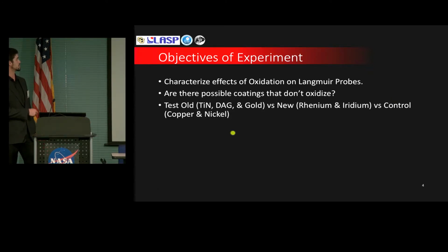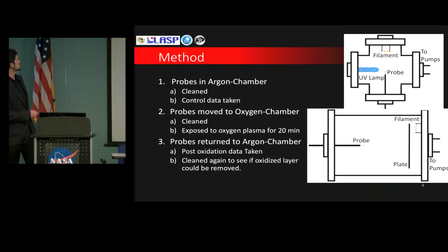And then we tested these against new coating materials, rhenium and iridium, in the hopes that those would not show any degradation. The reason we chose rhenium and iridium was that their oxidized layers are highly conductive, and our thought was that the oxidized layers in the previous cases might add a resistor in the circuit that would impede the current as you take the voltage sweep, and that would shift the curves. So in order to test this, we had a two-chamber method.